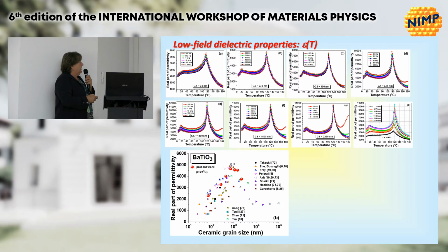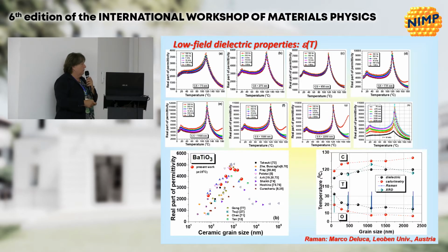The low field dielectric properties confirm this maximum, and with respect to other publications, we are in the high range of permittivities in these samples. And also we could reproduce this kind of temperature versus grain size phase diagram, which was completed with calorimetry and Raman data from Marco De Luca.